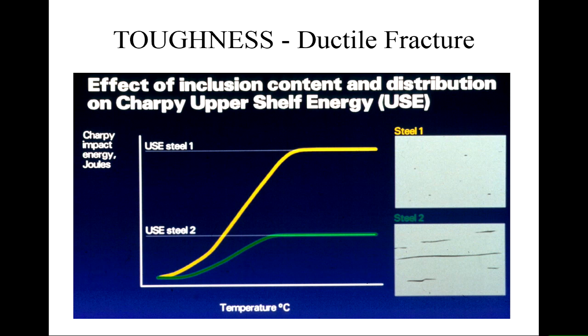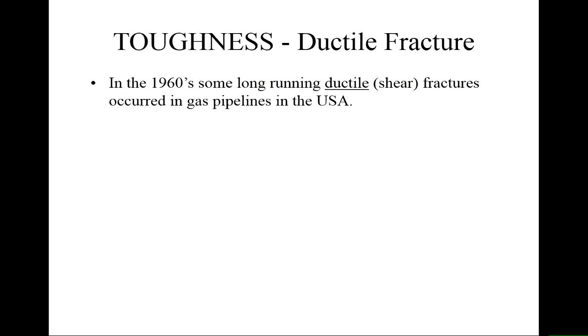These are, as I say, micron-sized defects. So why is this important? Well, we got some highly ductile failures in the US in the 1960s, and we say the words there long running, not because they lasted a long time, but because one defect crack produced a crack that unzipped a pipeline for a kilometre or more. So one defect, and then the pipe responds by propagating that crack, and effectively you destroy a large proportion of the pipe. And this was really related to the quality of the metal that was being produced.